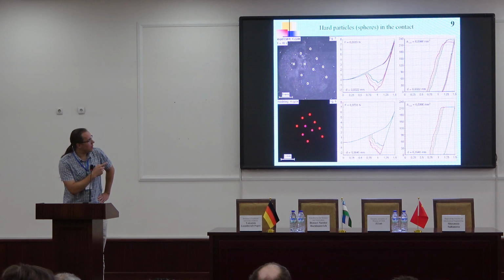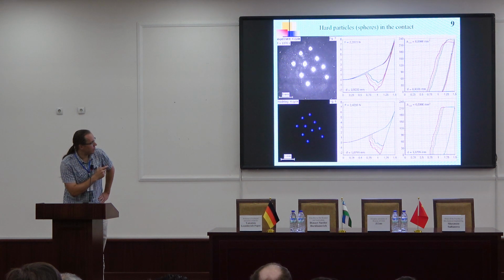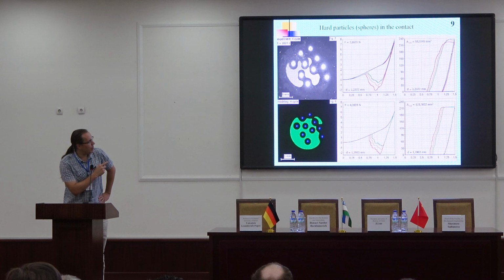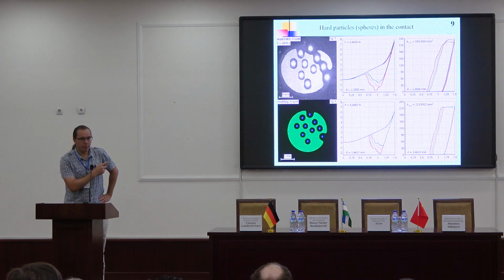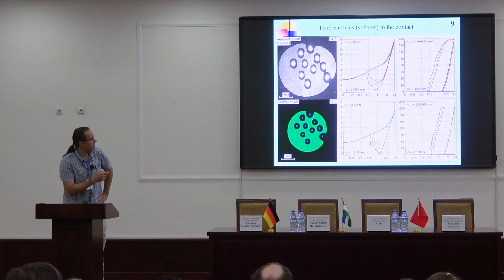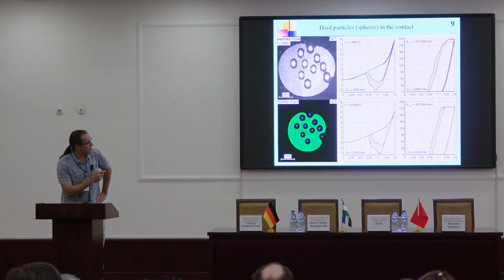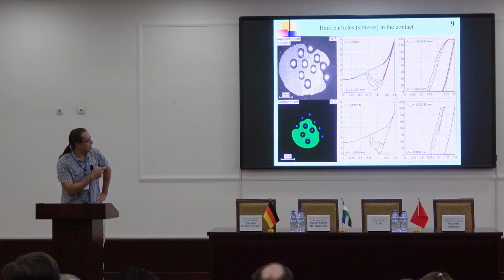And here I have shown the direct contact, this dependence of area of contact on indentation depth. It's direct contact between rubber and indenter, and you can see that we have direct contact at an indentation depth of approximately 0.75, in experiment and in simulations also. In principle, it's approximately the same contact area and contact shapes.